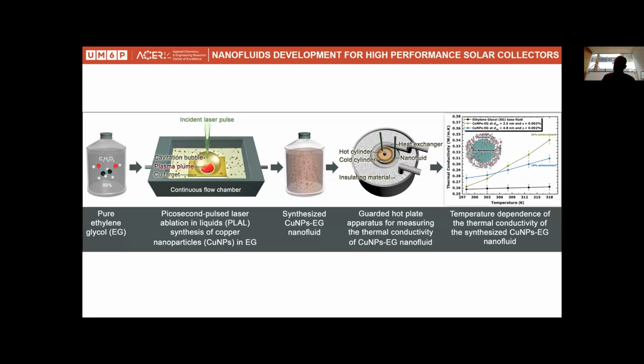Sometimes these nanoparticles can interact at different temperatures, and the nanofluid can lose stability in general. So here we vary the temperature and we measure the thermal conductivity with the system I showed you previously. What we can see here are copper nanoparticles in ethylene glycol, and at higher temperatures, the thermal conductivity is getting even higher. We achieved 30% and the stability was fine. We repeated this analysis from time to time, and the stability of the nanofluids was really good.